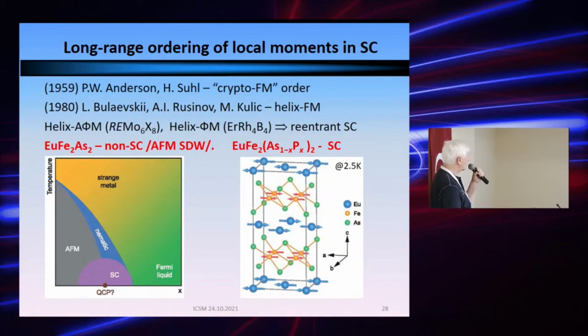And this indeed happens in the europium 1-2-2 system, which is non-superconducting without doping, and becomes superconducting only in the doped state. Since this, the exact way how the moments are oriented with respect to each other in different layers is a matter of a very fine competition of several driving mechanisms. Therefore, it's not necessarily happens in such a fashion where the moment changes by pi.